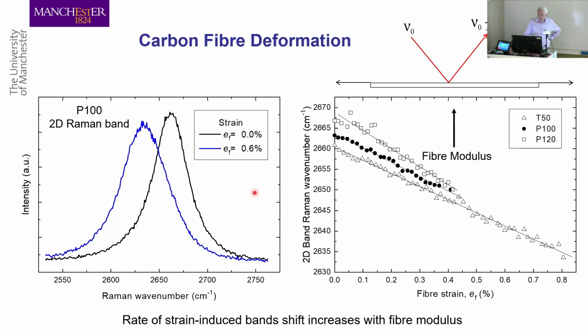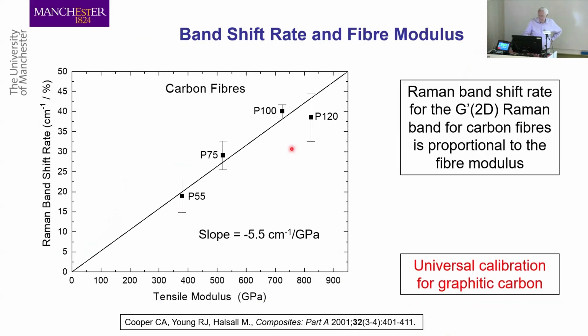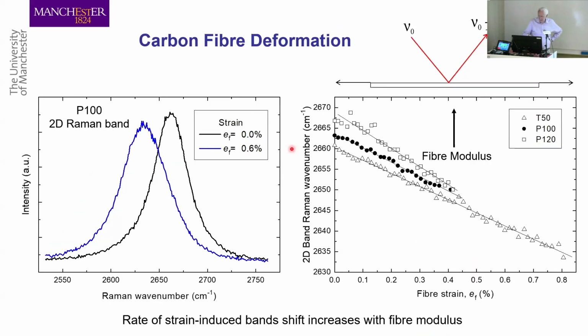And if you plot the peak position against strain, then you get pretty well linear behavior. And what we found was that the slope of this line tended to increase with increasing fiber modulus. The stiffer the fiber got, the higher the slope of the line. So the line just becomes a higher slope. And these are 3 different carbon fibers of different stiffness.